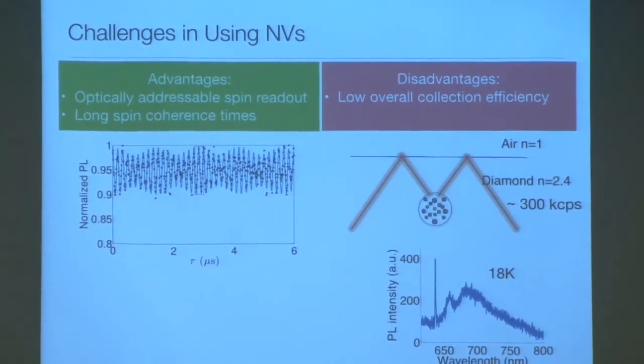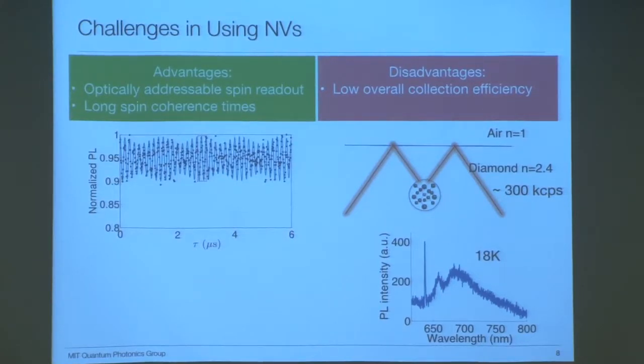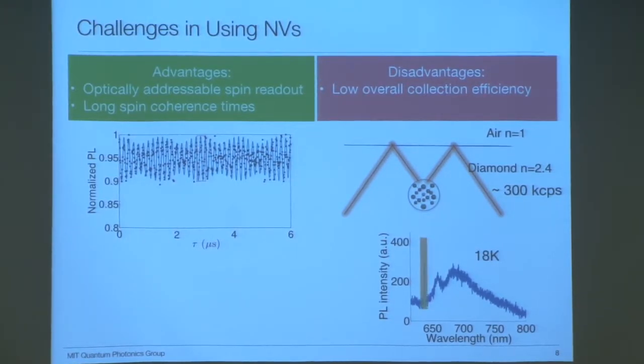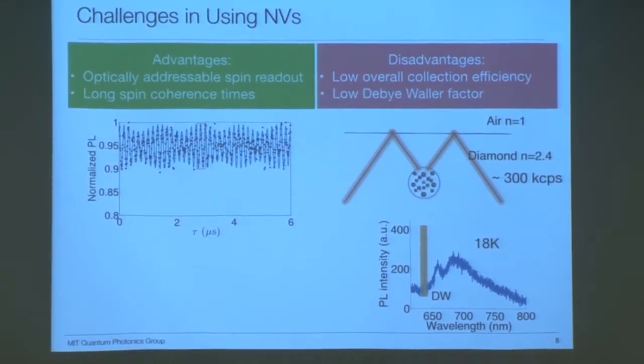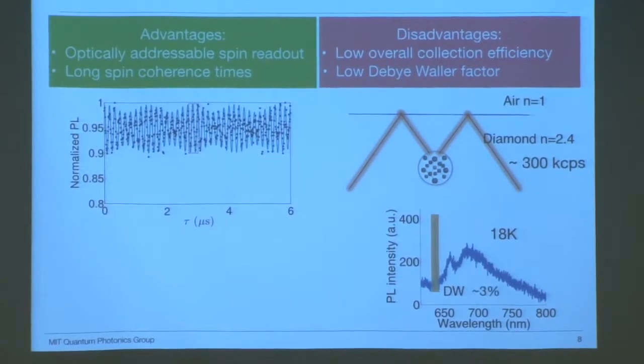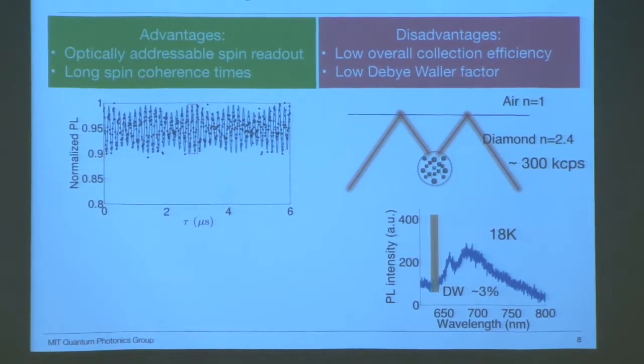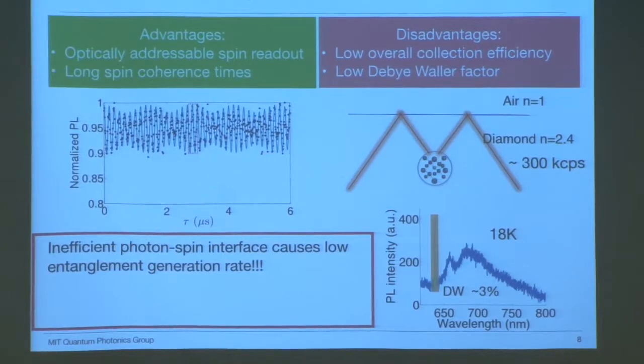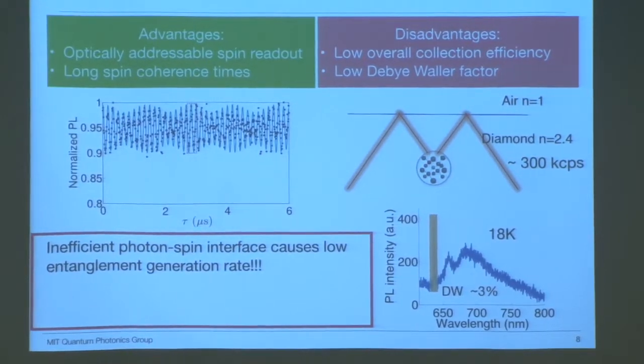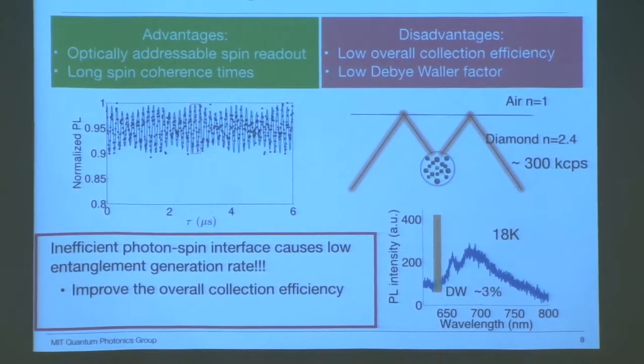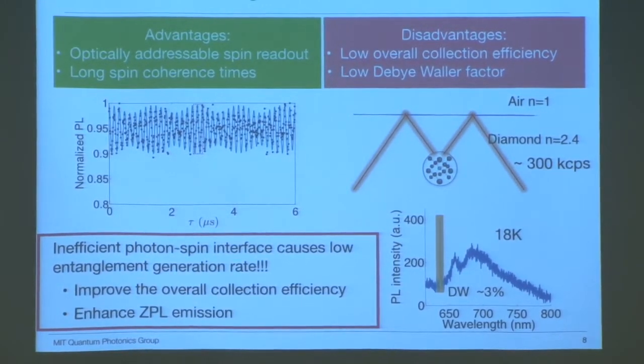And for optical entanglement of two NVs, the photon emission needs to be a coherent process. That means the photons must be in the zero phonon line. In the case of NV, we define this ratio as the Debye-Waller factor. And this Debye-Waller factor is also very low for NV. It's only about 3%. That means only 3% of photons are emitted through the zero phonon line. This inefficient photon-spin interface is the reason for the low entanglement generation rate. To solve this problem, we can either improve the overall collection efficiency or enhance the NV ZPL emission.